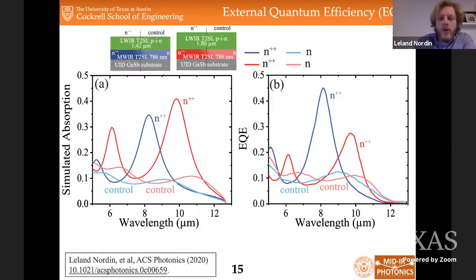So we grew these samples, we fabricated the mesas, we metallized the top and bottom, and then we performed spectral response characterization, responsivity, and EQE. And you can see our simulations match our experiment extremely well. We hit our target wavelength very well, around 8 microns and 10 microns respectively.